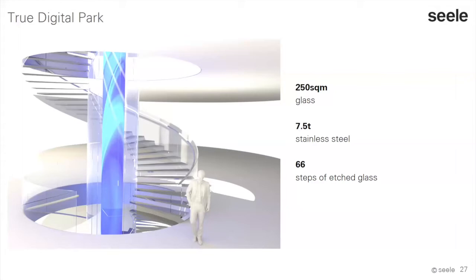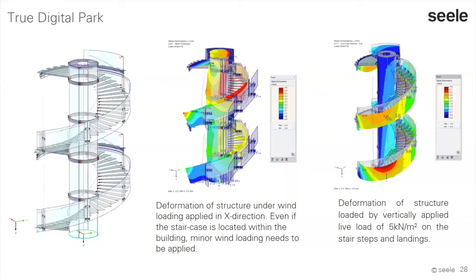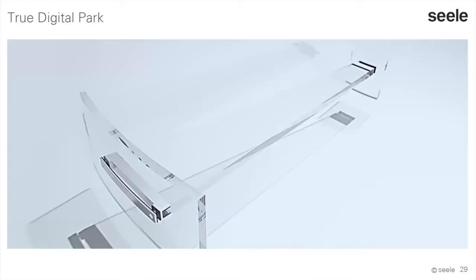So here you have the original architectural concept of it. 250 square meter of glass, 7.5 tons of stainless steel is in the construction here, and 66 steps of etched glass. The structural calculations here, you see the deformation of the structure under wind load applied in X direction here. Even if it's an inside staircase, you still have to apply internal wind load, which what we did here, and you can see the result on the glass structure. Then we did the visualizations.